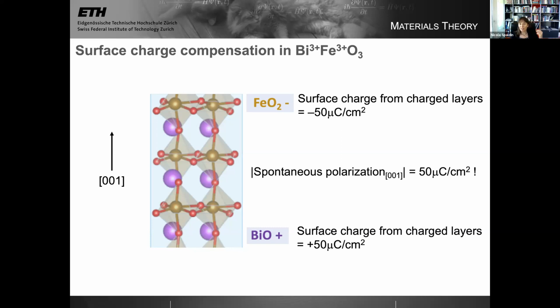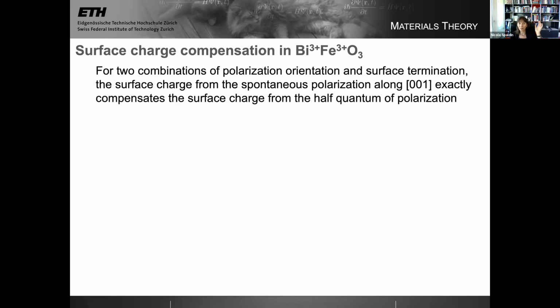So you can immediately see then, depending on how the polarization is oriented relative to these surfaces, I can end up with a net surface charge that's either very large or cancels out to zero, right? So I have two combinations of polarization orientation and surface termination for which the surface charge from the spontaneous polarization exactly compensates the surface charge from the charged layers, from this half quantum of polarization.